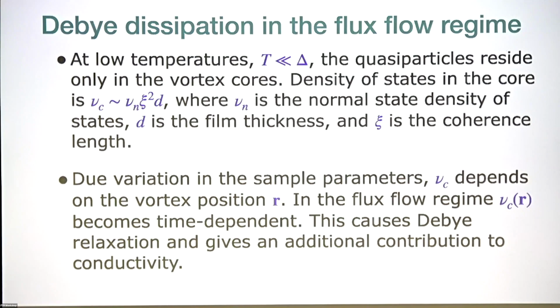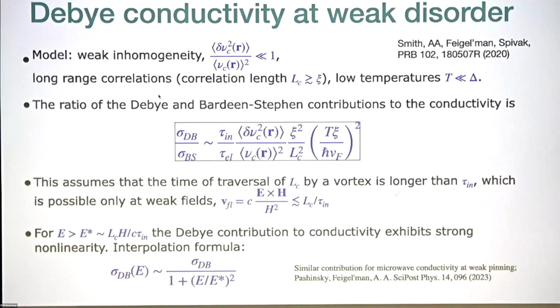And then as vortices migrate through the system, it will make the density of states in the core time dependent, and this will set off spectral flow and Debye relaxation. So then you can apply our old results for uniform systems, because cores are essentially zero-dimensional. And we did this with Misha Fiegelman and Boris and Mike Smith.